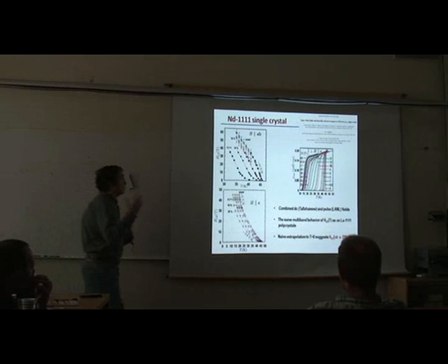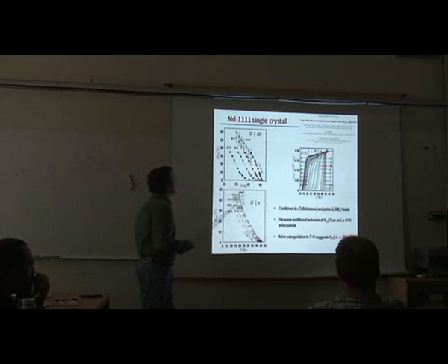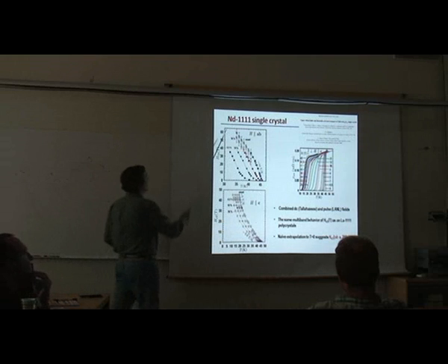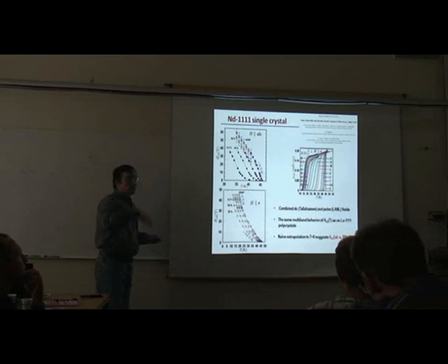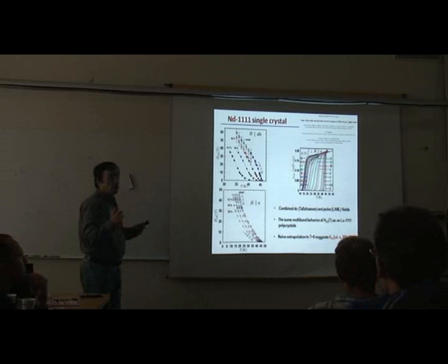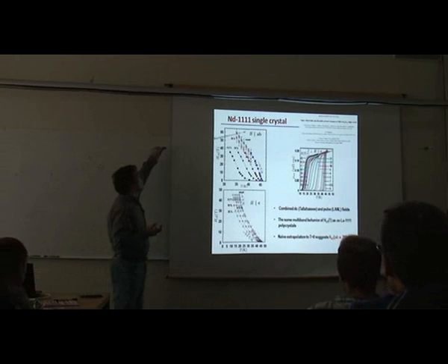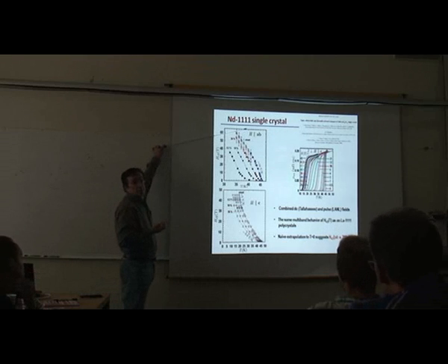And we did more careful measurements on single crystals. This is a neodymium-1111 single crystal. And Hc2 values become so high that we couldn't measure them because we stopped at 60 Tesla. That was done in Los Alamos.